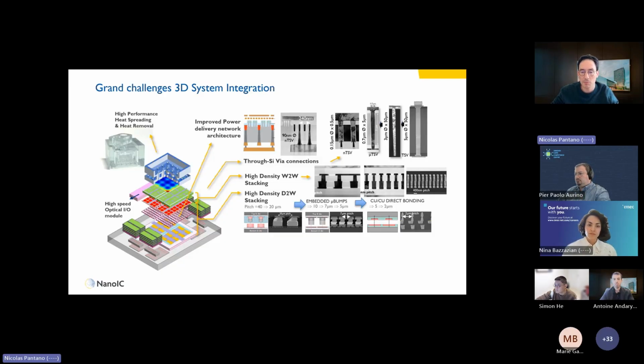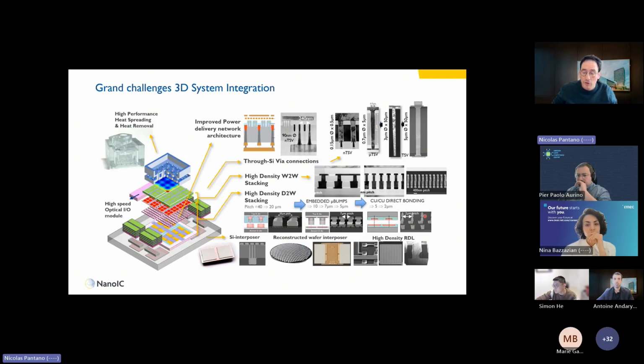We want to scale the micro-bumping. Maybe today we are in the range of 40, maybe 25 micron down to 20, or even below to 5 micron, which is probably a limit. And then to scale even further, we use the copper-copper direct bonding or the hybrid bonding, as you can see on this plot, on these images here. But at the same time, as I said, it's good to use a third dimension, but you also have to scale in the XY plane. And that's why silicon interposer, reconstructed wafer, high density RDL are still major technologies that are needed. And these are the technologies that we want to enable through the NanoIC Pilot Line, especially for the die-to-wafer hybrid bonding and the high density RDL.